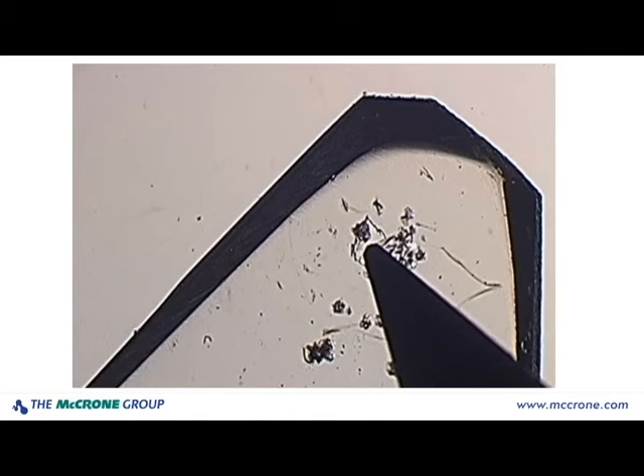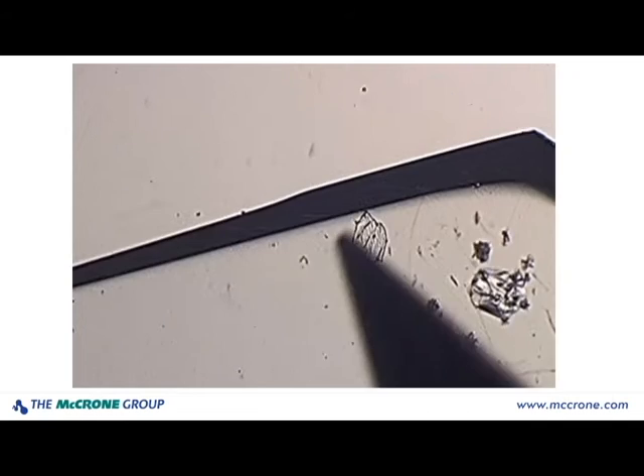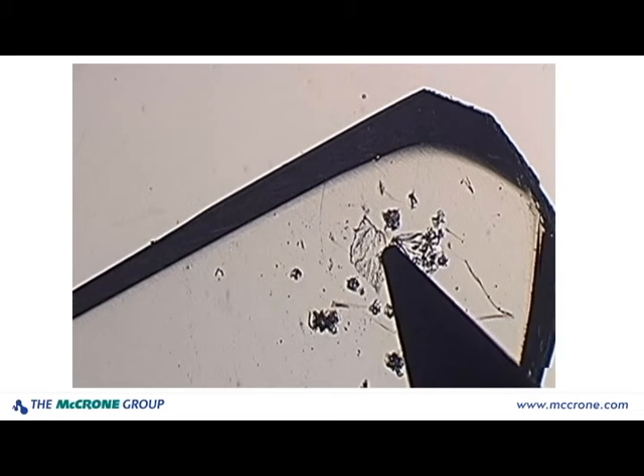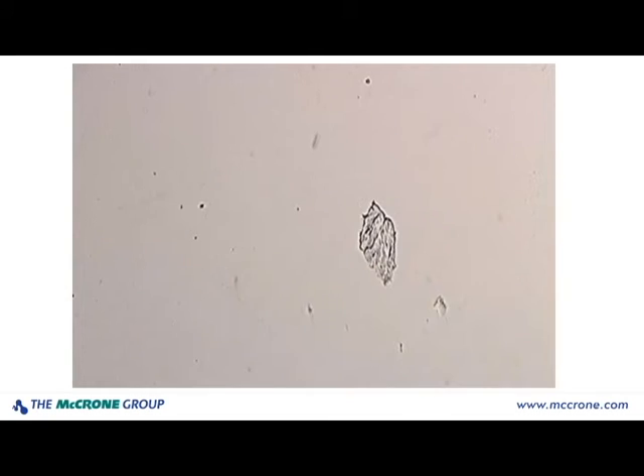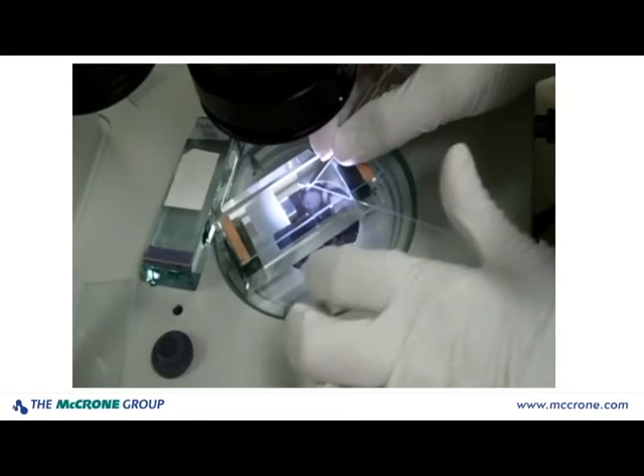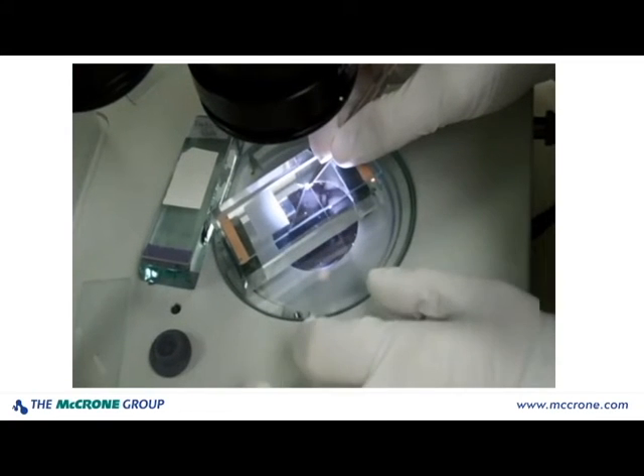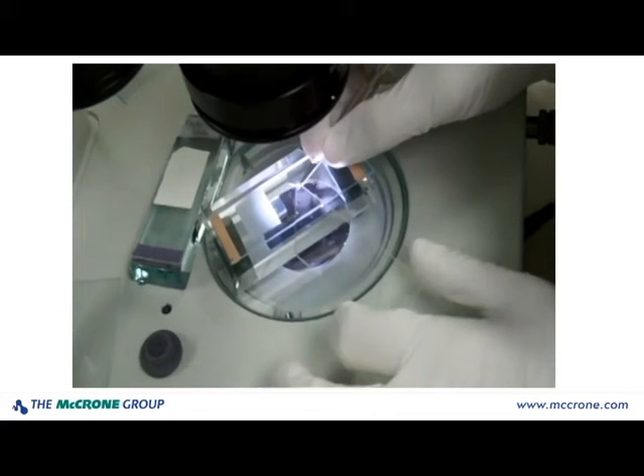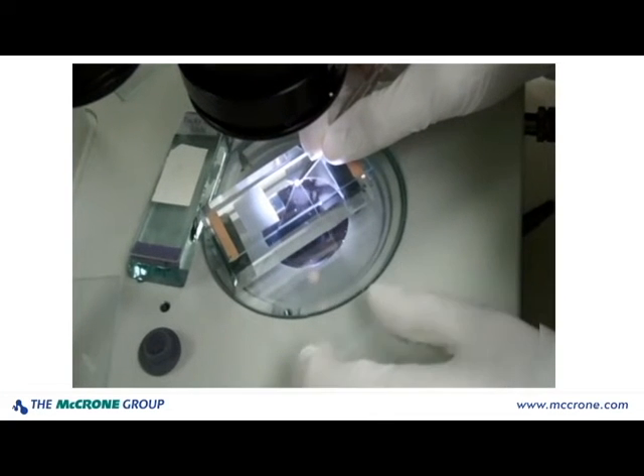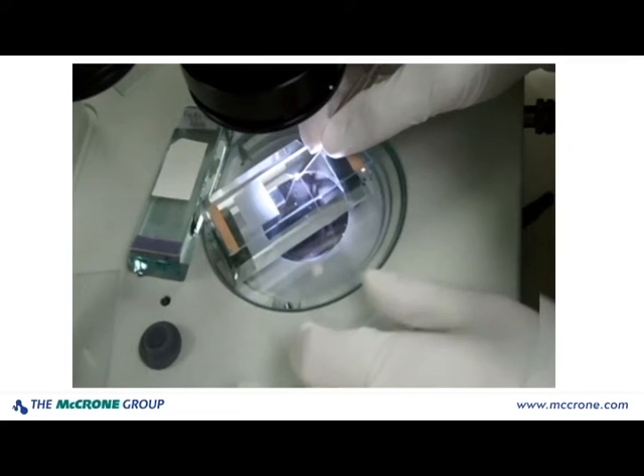I'm now going to place my glass wedge directly over my particle, and with the carbide scribe I'm applying pressure to the foot. I'm going to keep applying pressure and moving the wedge back and forth until I obtain a nice thin film. Now here again, the technique is going to be reviewed again, but this time from the side. You can see I'm applying pressure with the carbide scribe, and my opposite hand is moving the wedge back and forth until my sample is thin enough.